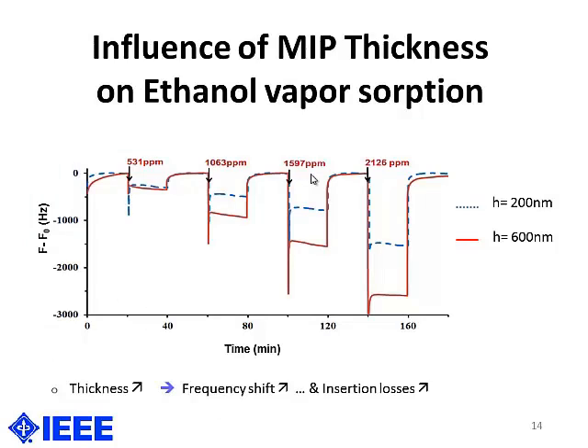On this slide, yes, I have some time, just to illustrate the influence of the MIP thickness during ethanol vapor absorption. In fact, we have found that, of course, with the greater thickness, there is a greater sensitivity, but also more insertion losses. And in fact, we have found that a layer of a few hundreds of nanometers was a good compromise for both a good sensitivity and low insertion losses.